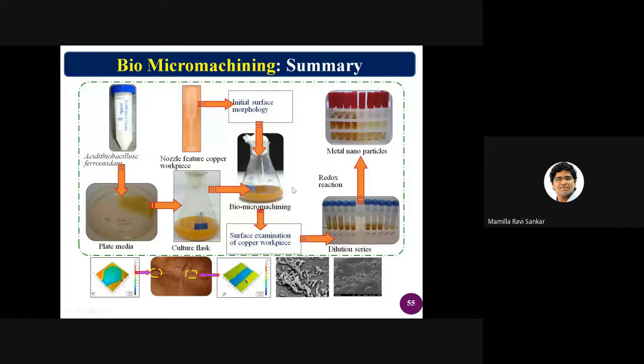This particular paper was judged the best paper award in 2017 at IIT Madras for two reasons. One, we are not getting any thermally damaged or metallurgically damaged layer. We are getting perfectly fine micro features on copper. At the same time, we did this on copper because we can also get nanoparticles, and these copper nanoparticles are highly pure.